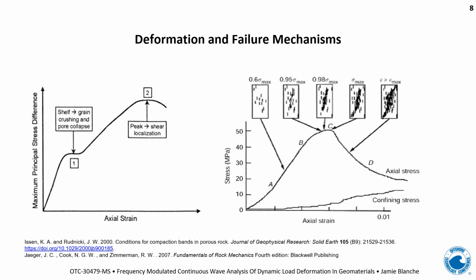Now, once some of that pore crushing accommodation space has been taken up, then the sample is able to resist load again. So you start to see this increase in gradient until you get to the point where you've reached the end of the material's capability to resist that load, and you start to see wholesale fracture within that sample. So if I move on to the right-hand graph, this gives us a bit more of the evolution of that.